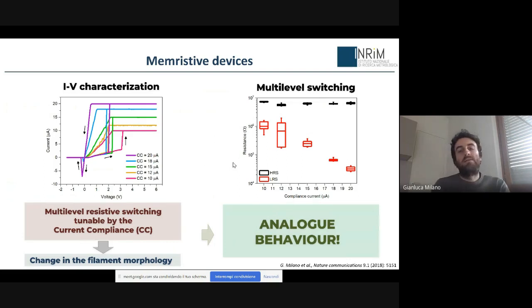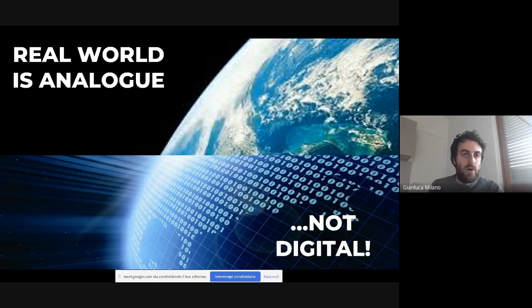So what is the main advantage of these devices? Well, it is possible, by controlling the operational conditions, to tune the internal resistance state with multi-level capabilities. So we don't have only 0 and 1 as in transistors, but we can have an analog behavior. For example, we can tune the low resistance state across more than one order of magnitude. This is something that we have demonstrated in single nanowire devices, thanks to the control of the filament morphology that depends on how much current passed through the device. So we have an analog behavior in these devices. And if we think about the real world, everything is working in an analog way, not in a digital way.